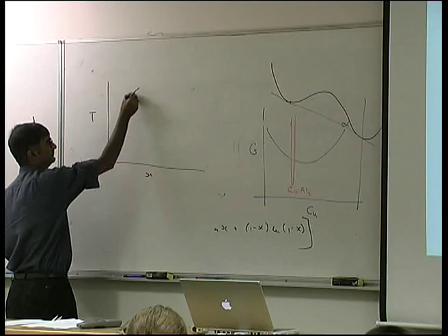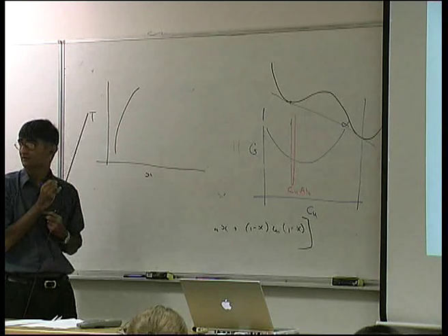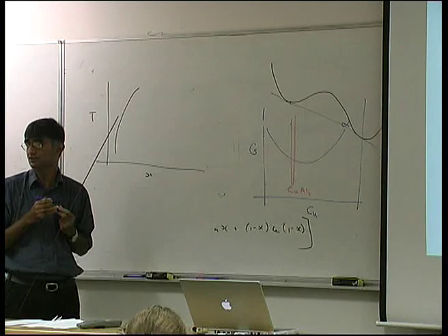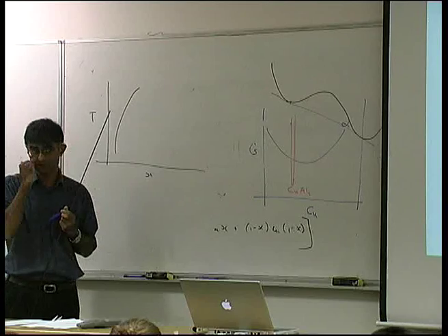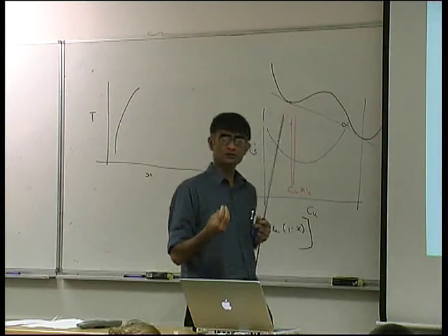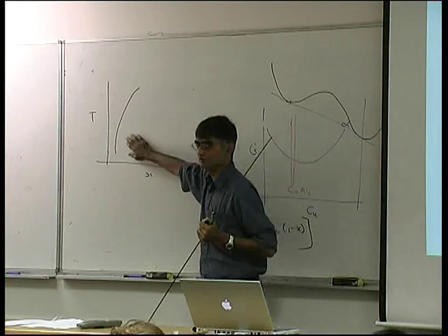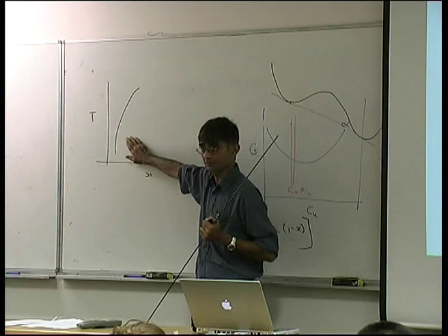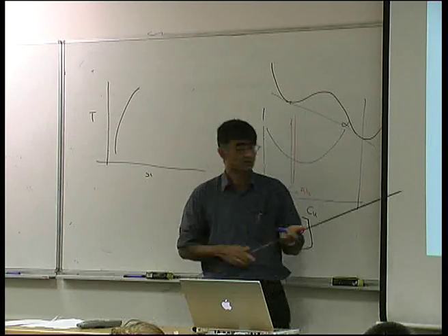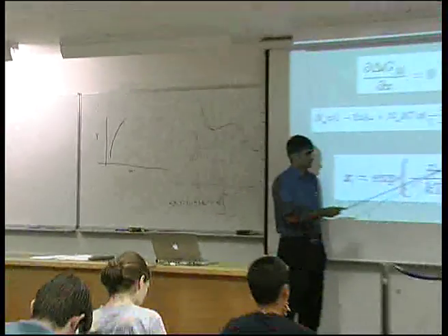Solute and phase boundaries look like this. Okay? So that's exponential variation of solubility as a function of temperature. So in order to calculate this phase boundary, which is the most important boundary in the heat treatment of aluminium alloys, we only need one term for a given solute.